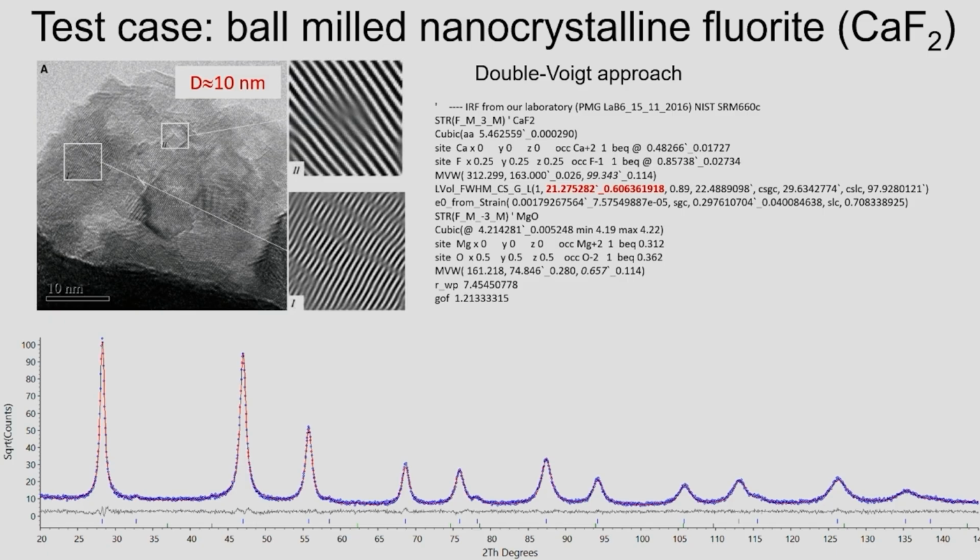And of course, they don't move easily because it's ceramic, but you can create them. So this is just to say dislocations are everywhere, but remember, in your material, only rarely will it be the only source of broadening. So you better use that Warren plot if you want to have the total information. The dislocation density, keep it with a grain of salt, is an upper bound.